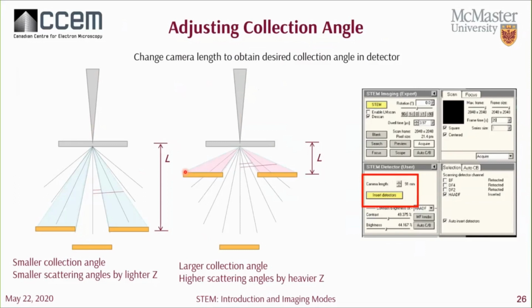It's good to note that from this you can get quantitative information from these images. You want to quantify the number of atoms that you see in a column using the intensity from your images. In reality, it's just difficult to do. You need to simulate the image that you'll see. You'll need to calibrate your detector to measure the dose. And also, you'll have to think about your sample. It's subject to surface contamination and things of that nature. And so generally, we take a more qualitative approach in which you like to confirm whether your sample contains certain elements or layers of interest.